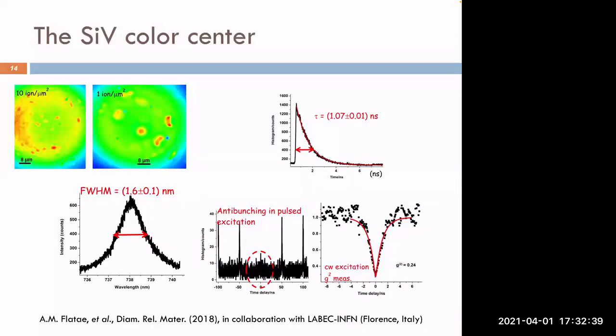And here is basically what you can get. You see in the picture of the two camera images, two different situations. So in the left panel, you have 10 ions per square micrometer. And in the second, you have 1 ion per square micrometer. So you can change the ion dose in the accelerator in order to implant more or less ions per area. And this is very important to determine whether you can get a single photon source or not. So typically, we need to go for 1 ion per square micrometer in order to be able to address a single photon.